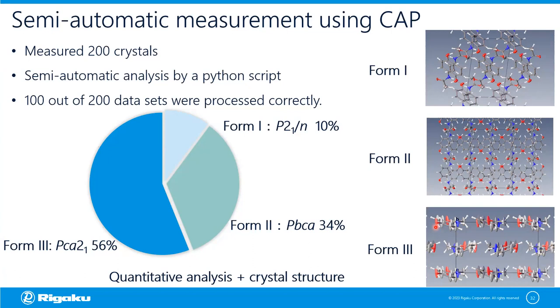And what he found was, under the conditions of that crucible that you saw, 56% of those were actually form three, 10% were form one, and 34% were form two. There were no other forms in that analysis. So we have the structure of form one, we have the structure of form two, and now we have a single crystal structure of form three. And what you'll notice here is that the structure doesn't look so hot. We've got lots of very extended thermal ellipsoids. Some are quite flat. You know, this would raise flags for any editor of Acta.